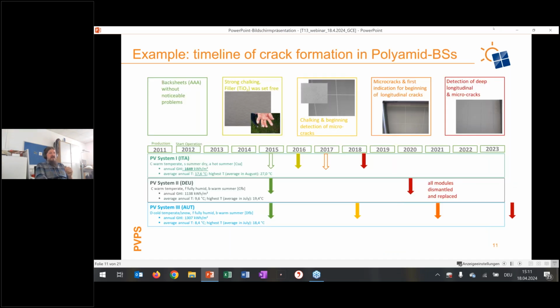So how do these cracks form? This is an example of one of these infamous failure cases where a so-called polyamide backsheet showed this type of cracks. And you see, depending on the climate, it takes several years for the cracks to form. In most cases, the first observation was chalking, meaning when you touch the PV panels on the backside, you had a white powder on your fingers that is basically titanium dioxide, where the top polymer surface layer was eroded and the titanium dioxide was set free.